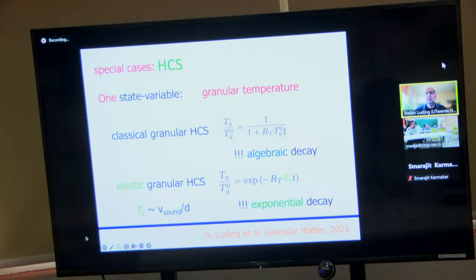Take the granular temperature, it's decaying algebraically in a granular gas. In the gas or fluid state, the decay is algebraic, 1 over time for long times. In the elastic system, above jamming, it's exponential. So the theory makes a difference between the fluid state and the solid state. You see algebraic versus exponential decay, and this was a surprise for me, because the exponential I didn't know. I saw it in the theory first, and then I looked at my simulations again, and actually the simulations confirm what I observe: algebraic versus exponential in a fluid or in a solid.